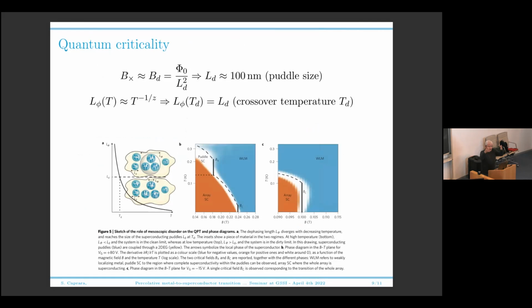have broken superconductivity inside the superconducting island, you have introduced the quantum flux inside an island. But you know the experimental value of the magnetic field that breaks superconductivity in the islands, according to our interpretation. You know the value of the quantum of a flux. And then by this ratio, you get that your puddles are in the order of hundreds of nanometers. So you have to imagine that each superconductor, this is the typical size. Maybe, of course, in the real system, there is a distribution of different sizes, but this is a typical size of the puddles, which we estimate in the order of 100 nanometers.